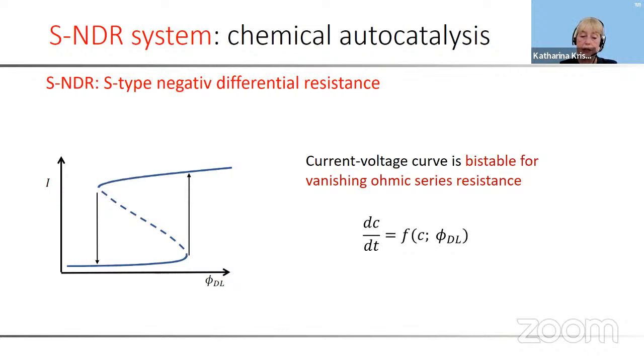And if we have a chemical autocatalysis, for the bistability you do not need an ohmic resistance in your system. So the electrode potential in the first place degrades, let's say, to a parameter. And such systems have an S-shaped current potential curve, where now the S is due to the electrode kinetics. The bistability alone can then be described by a single variable in principle.